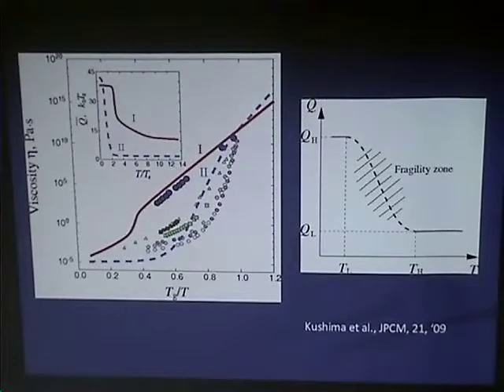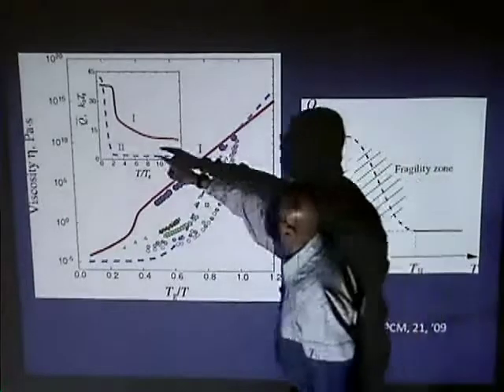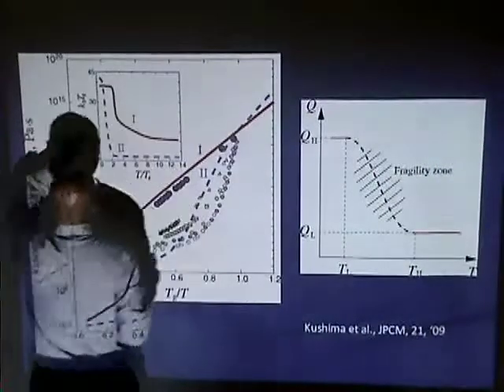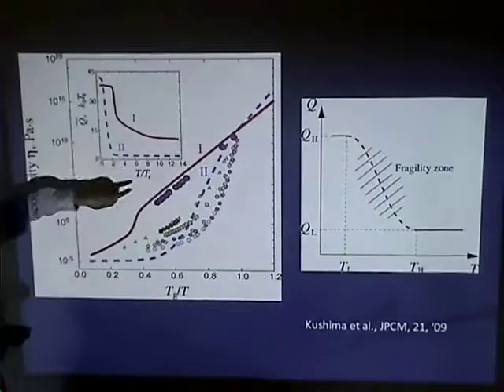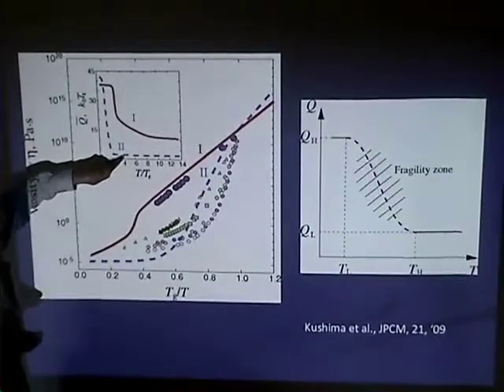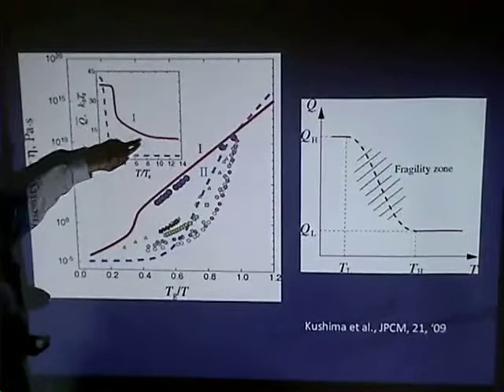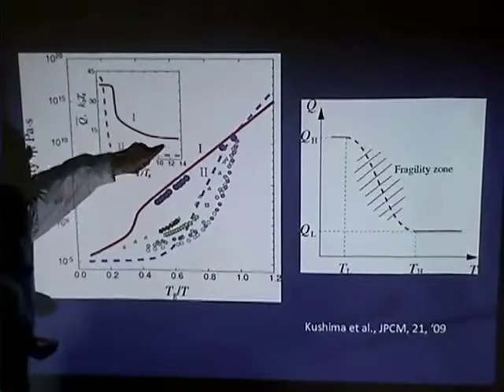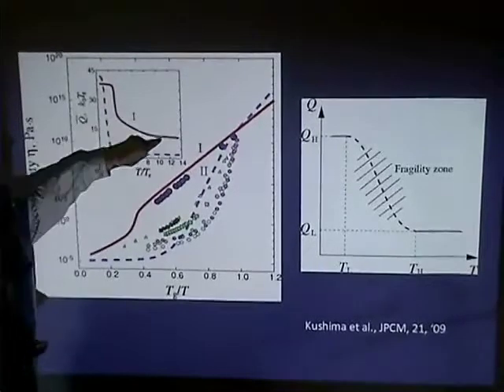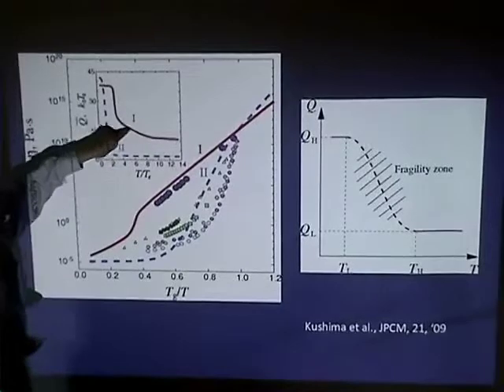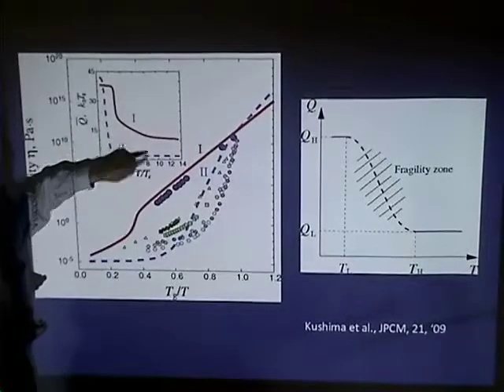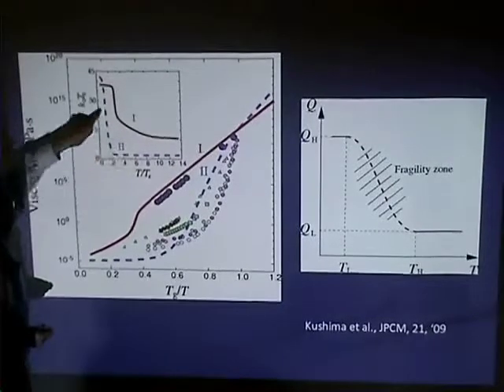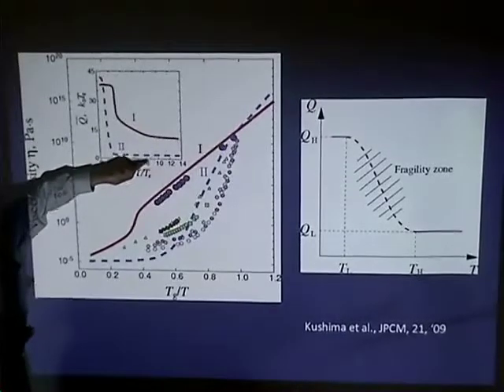All right, since we have done the calculation of the viscosity here, here's a plot of the effective activation barrier as a function of temperature for silica, a strong glass former, and binary Lennard-Jones, a fragile glass former.